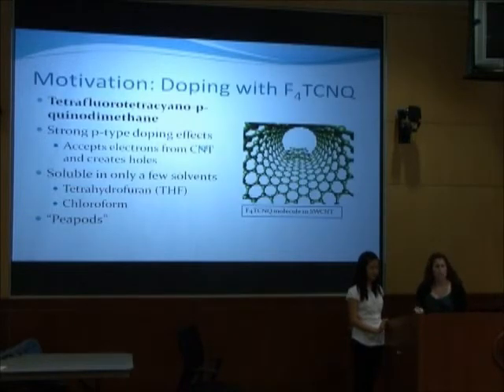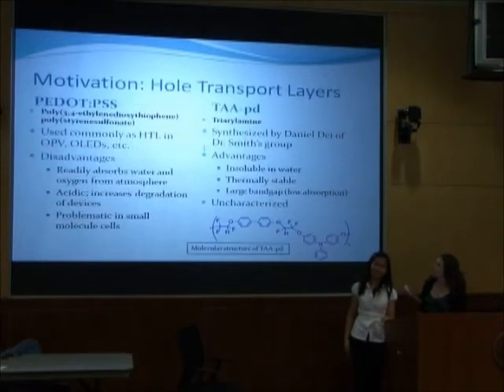So we mentioned doping, but how about the dopant? We used tetrafluorotetracyanoquinodimethane, otherwise known as F4TCNQ. F4TCNQ is a P-type dopant. It's only soluble in a couple of solvents such as THF and chloroform, and it's been known occasionally to pea-pod. Pea-podding means that a molecule of F4TCNQ goes inside carbon nanotubes when you dope them, which is in the picture.